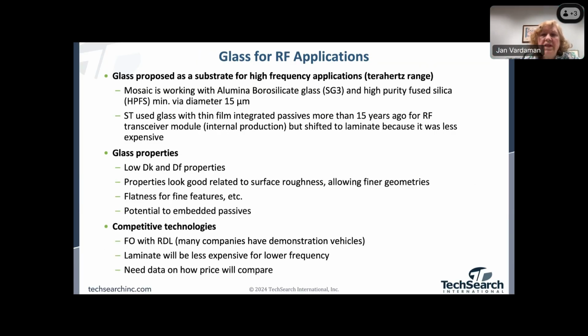So we see a lot of application potential in RF. For example, glass has been proposed as a substrate for high frequency in the terahertz range. So we have companies like Mosaic that's been working with aluminum borosilicate glass and some high purity fused silica with a minimum via diameter of like 15 microns.